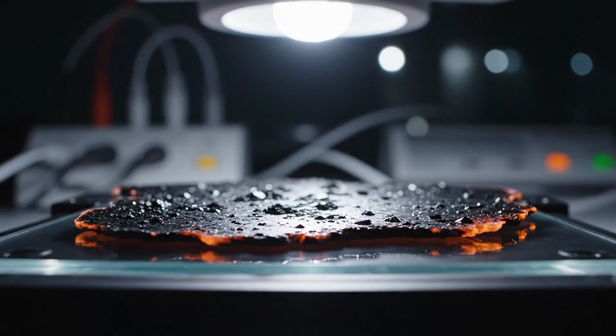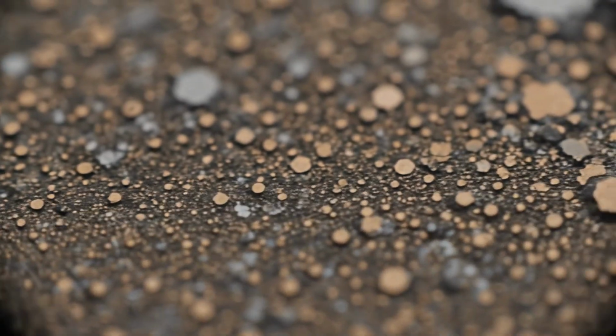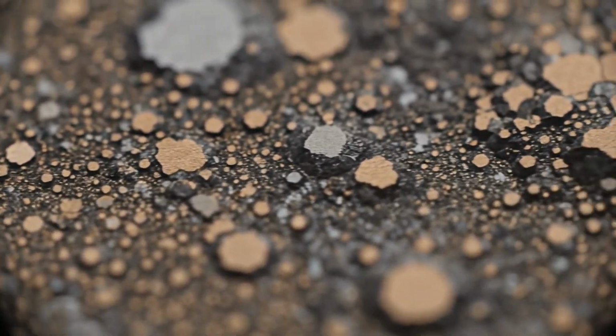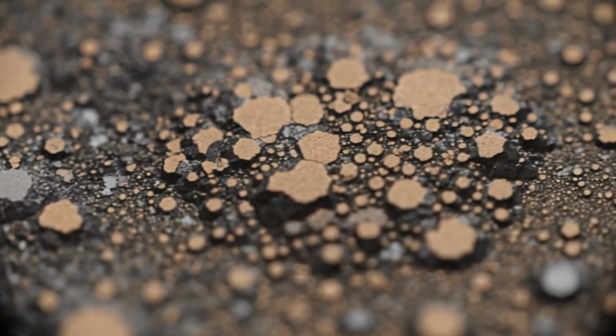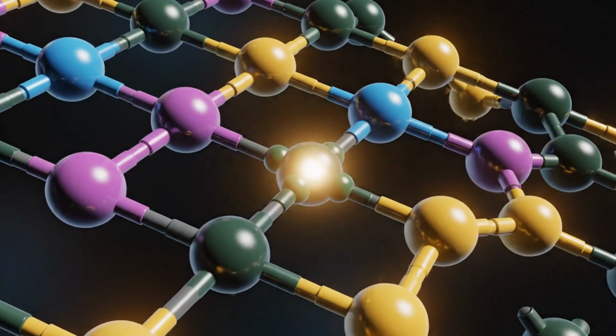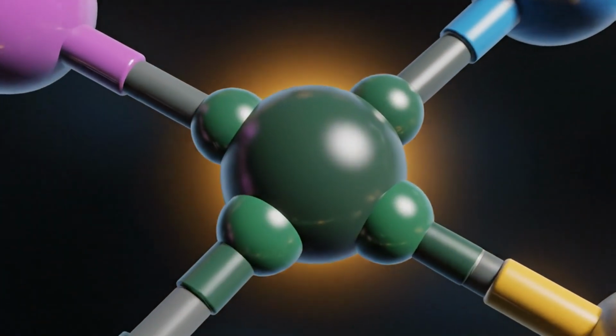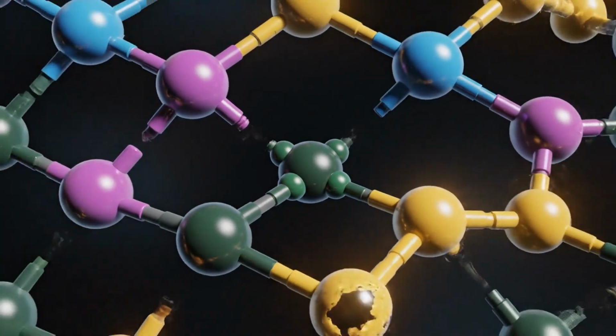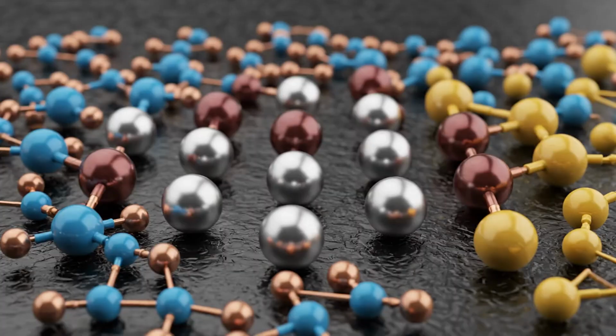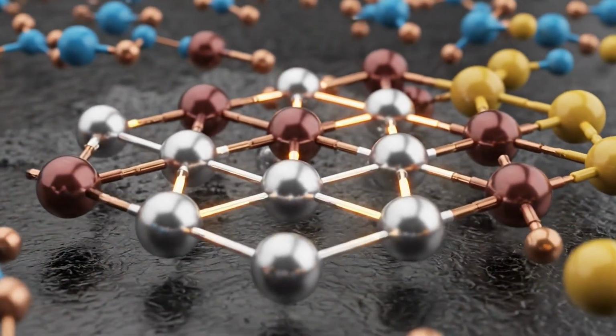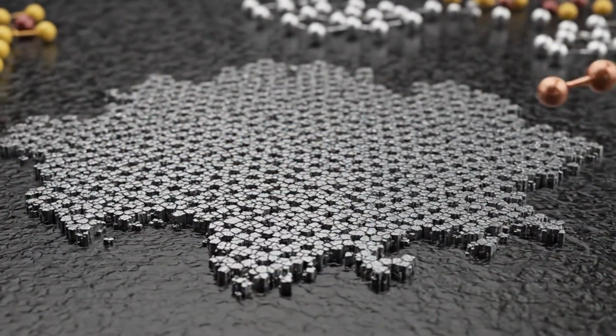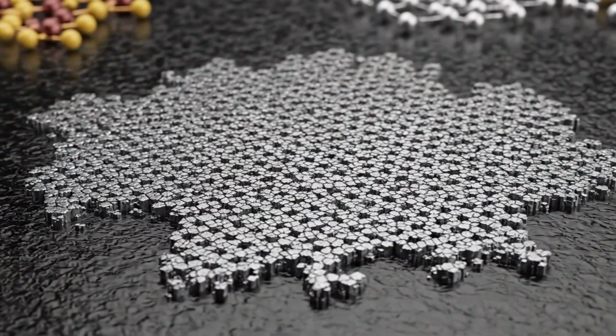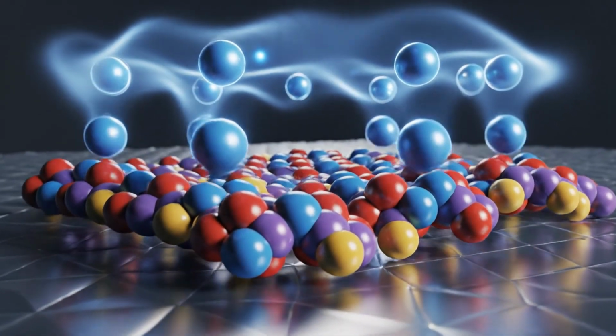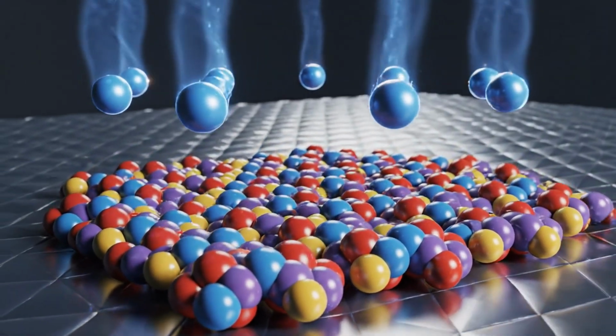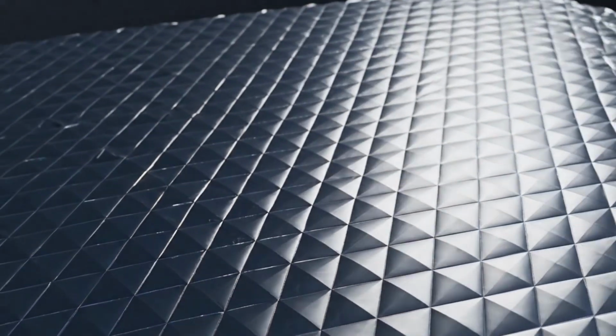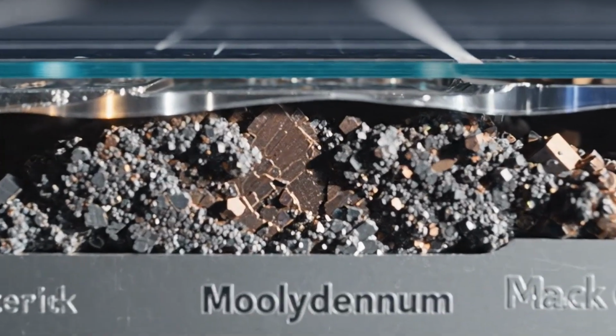The controversial shortcut: alloying. There's also a more controversial strategy. Instead of insisting on absolute material purity, some researchers have experimented with tiny amounts of foreign elements. Small additions of silver, germanium, or even cadmium can help guide atoms into their correct positions during crystal growth. These elements act like scaffolding, temporary guides that encourage a more ordered structure, and the results are hard to ignore. Using these techniques, researchers have achieved record-breaking kesterite efficiencies in the lab.